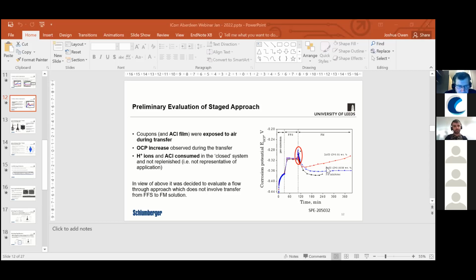So first, the thickness of this polymeric film is very, very minor. It's about a few nanometers, maybe 10 nanometers. So it's very conductive, so it's no problem with corrosion measurements. But concerning the flow speed, in our Corrosion Science papers we published several papers on investigating the effect of flow on corrosion for acidizing conditions. When we conduct RCE, rotating cylinder electrode, at speed 6,000 RPM, the flow conditions, that means wall shear stress and Reynolds number, are very similar to performance in real coiled tubing applications. For example, when we pump 2 barrels of acid per minute via coiled tubing about 1 inch in diameter. So it's real highly turbulent flow conditions, and we actually investigated under these highly turbulent flow conditions. It was presented in some slides in Josh's presentation.